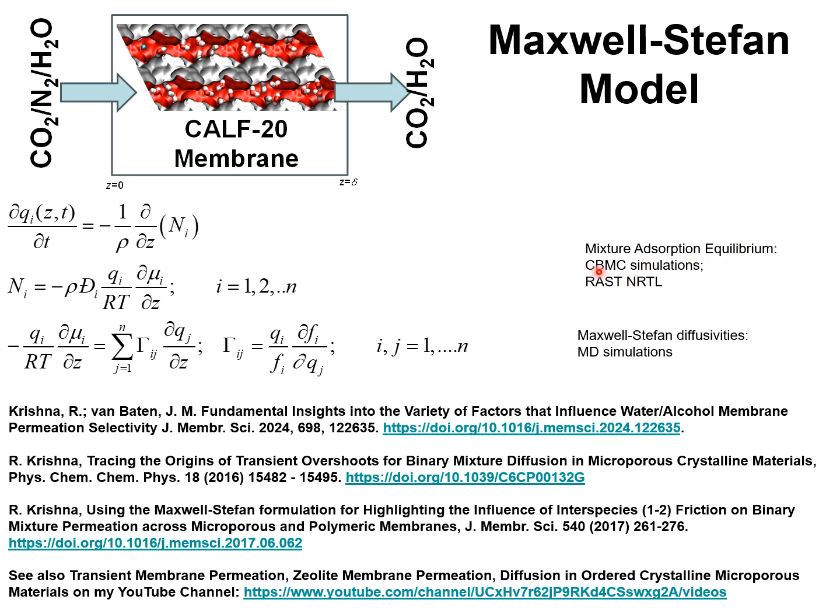I use configurational bias Monte Carlo simulations for the mixture adsorption equilibrium, and the CBMC data show that the mixture is strongly non-ideal and requires the quantification of deviations from ideality. In this particular case I use the NRTL model for quantification of the activity coefficients in the adsorbed phase.